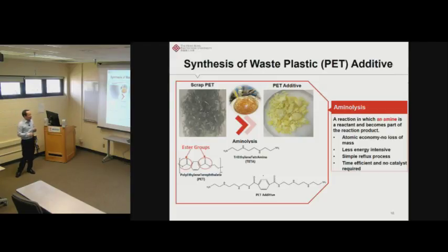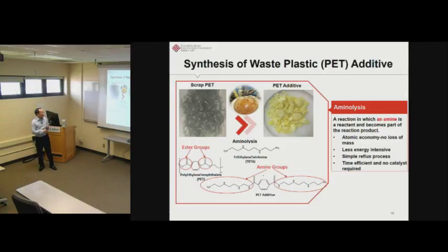And during the reaction, actually what happens is in our PET material, we have some ester groups. These ester groups are actually relatively weak groups. So they can be easily attacked and replaced by these amine groups in the amine material we use. So after the reaction, you will notice the ester groups will be replaced by these amine groups.